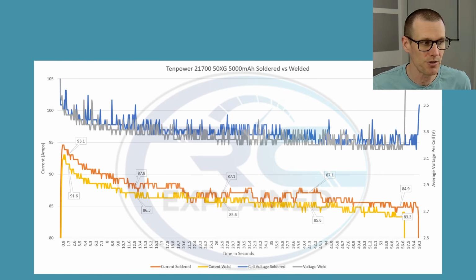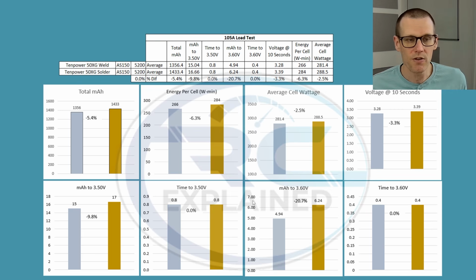Also note that when we look at our load test, because we have such a significant voltage drop because of that internal resistance, our 105 amp load test is no longer 105 amps. It actually drops down almost to the 85 amp mark on average, probably averaging around 87 to 85 amps. So now going back, let's take a look at all the elements there.